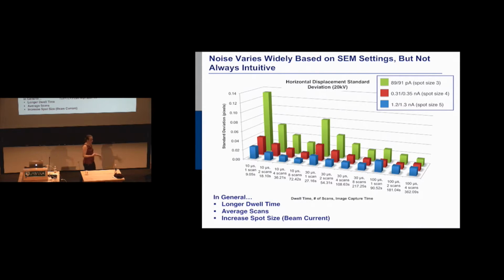Doing a noise parameterization study is important for any type of characterization in the SEM. The only thing I want to show you here is, in general, yes, longer dwell time, average scans, increased spot size. However, spending a really long time getting your image in an SEM doesn't mean that you're going to have a better image. You could spend 360 seconds getting an image, and you would get this noise. You could spend 18 seconds getting an image, and you would have this noise. So longer time doesn't always equate to a better image.